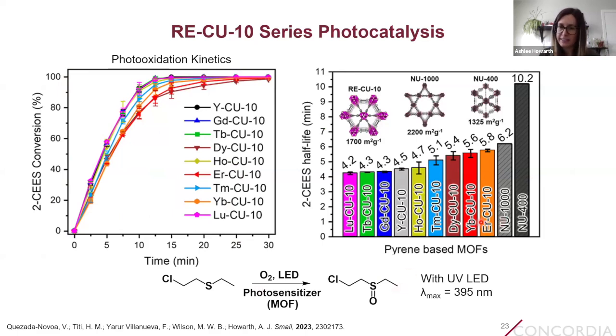Also, in all cases, we still see that the catalysts are faster than the zirconium-based MOFs with pyrene linkers, NU-1000 and NU-400. So that's also great. But we do see that some of the MOFs where energy transfer is possible do have longer half-lives or slightly slower photooxidation kinetics than the others, suggesting that there is a bit of competition between that energy transfer pathway and the generation of singlet oxygen, which slows down the half-life just a little bit.